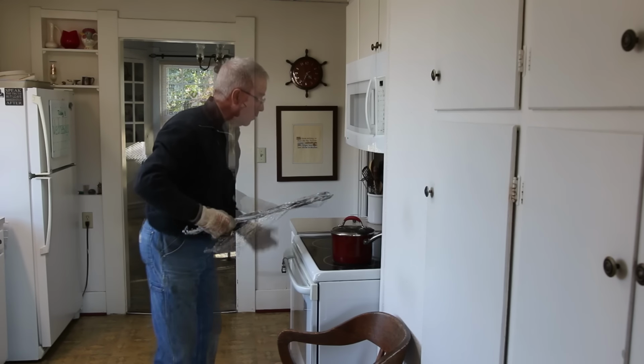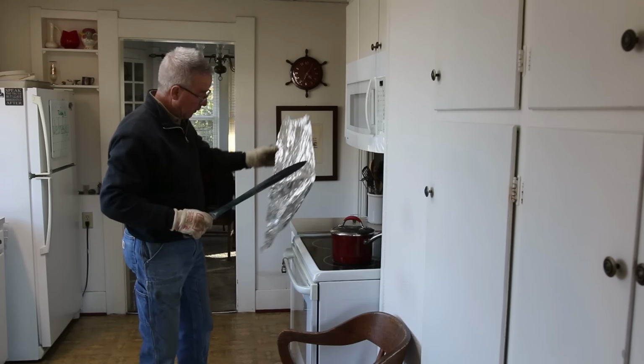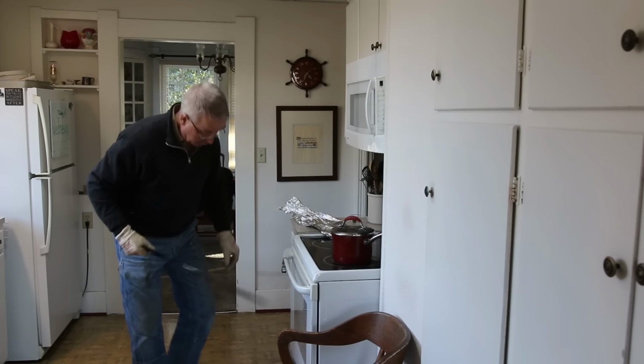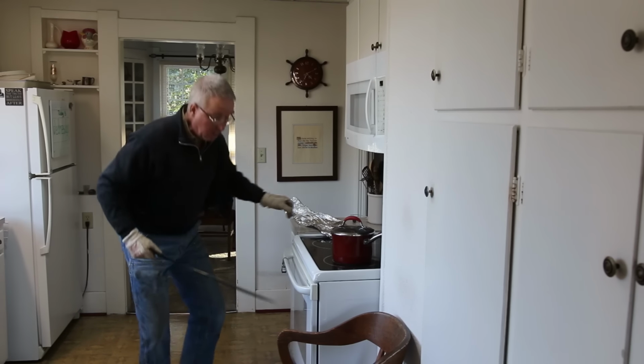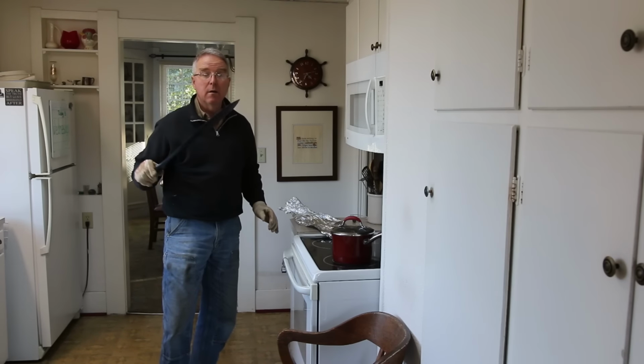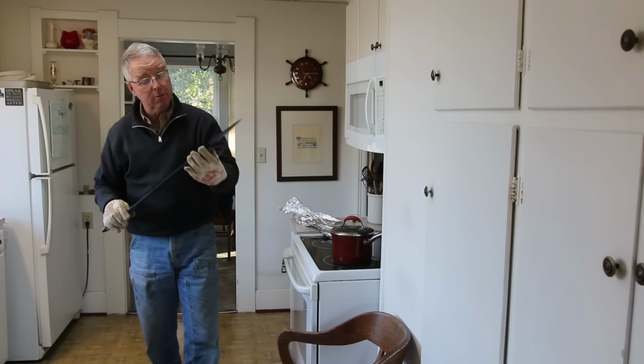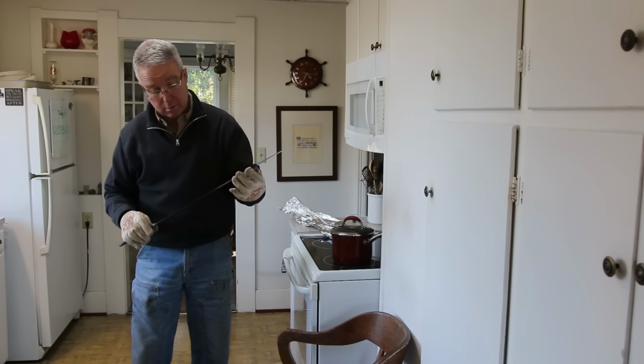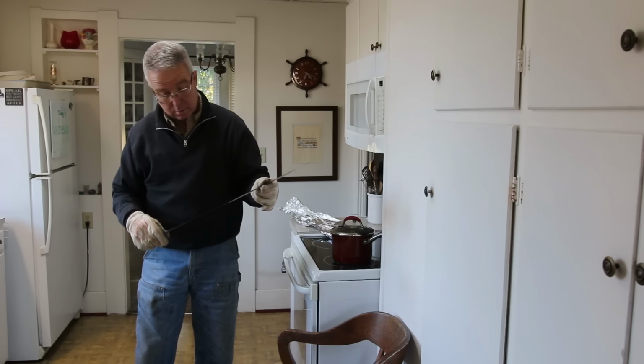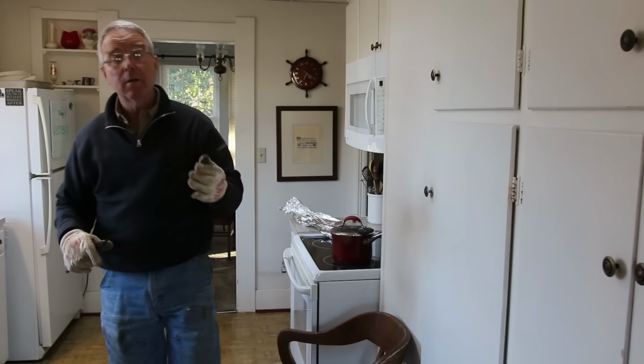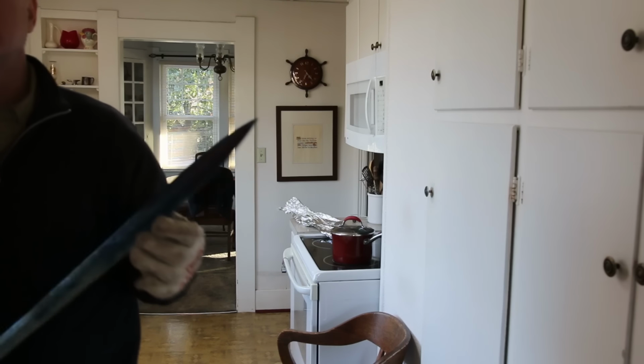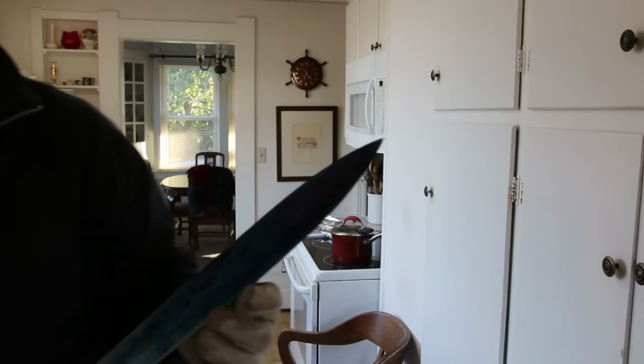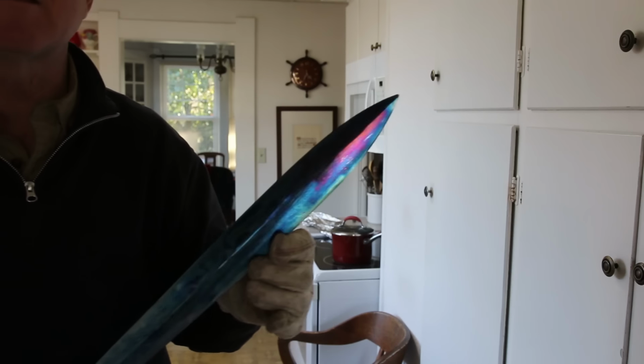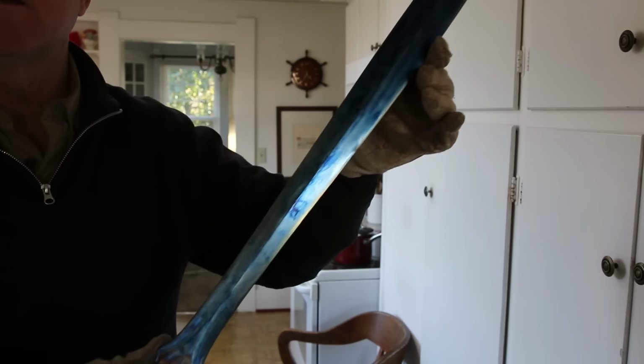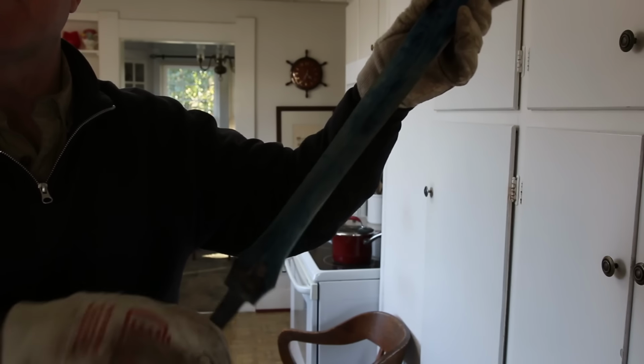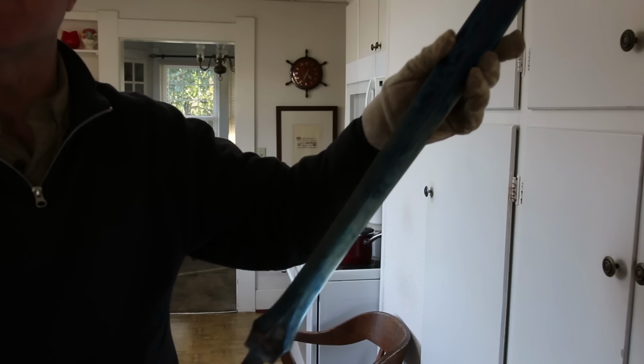Tempering is the final step in heat treating, and it means slowly heating the steel up to the temperature that will draw it back or soften it to the compromise between hardness and springiness that the tool needs. In the case of a sword, that is a spring temper, around 550 degrees or so, and a full royal blue color. How nice the spring temper blue is on that. I would never be able to get it that nice with a torch.